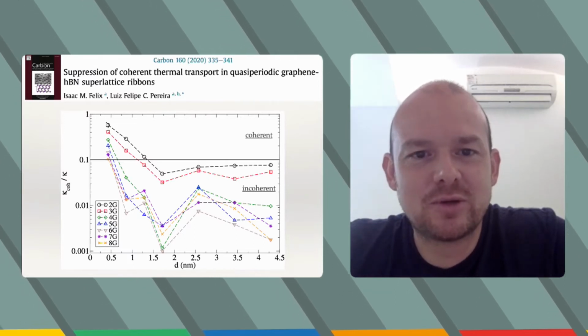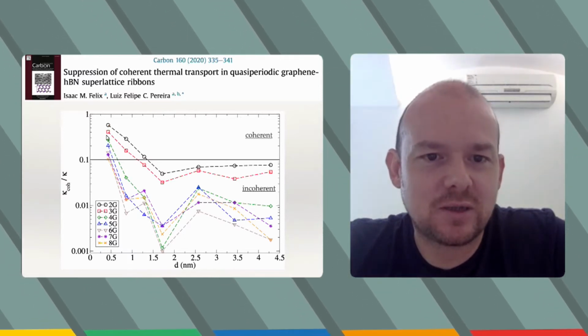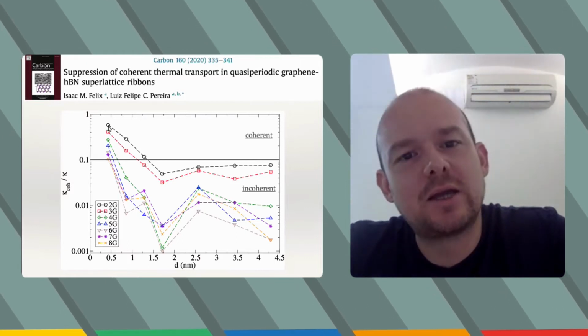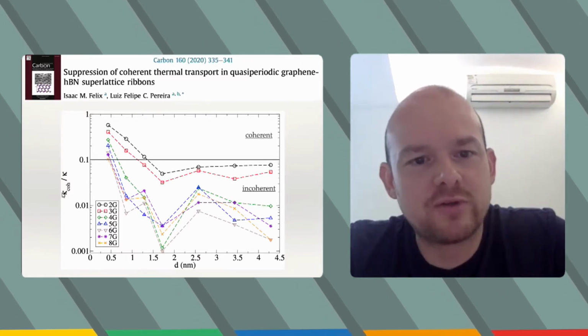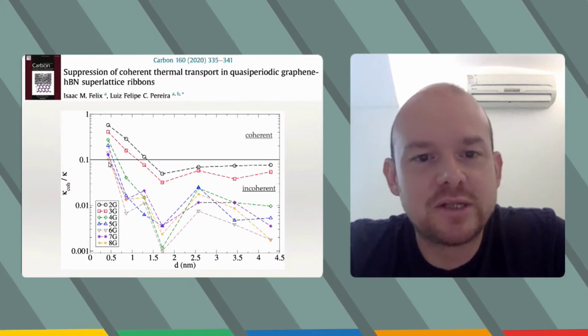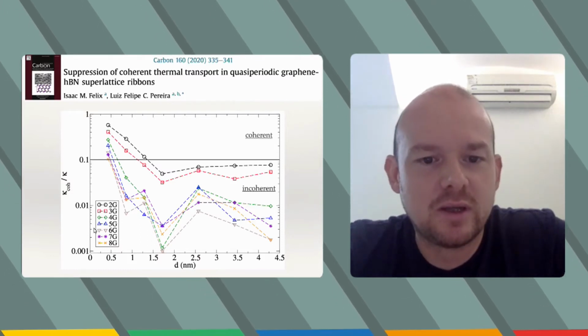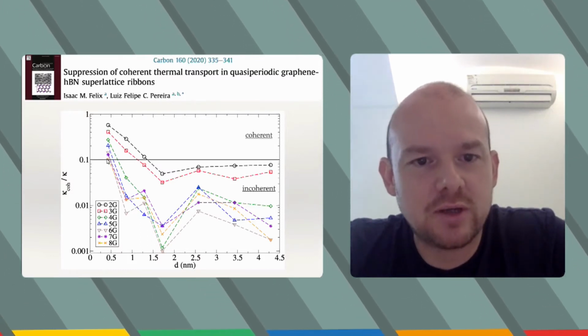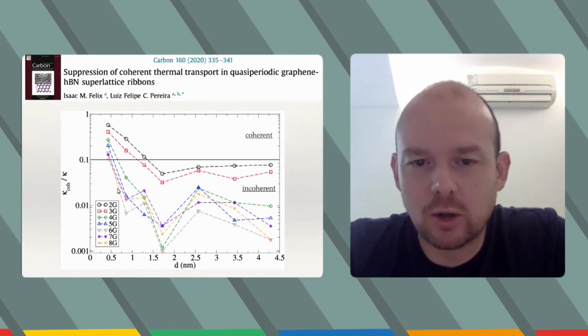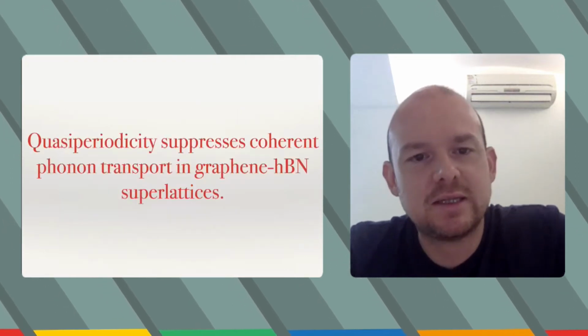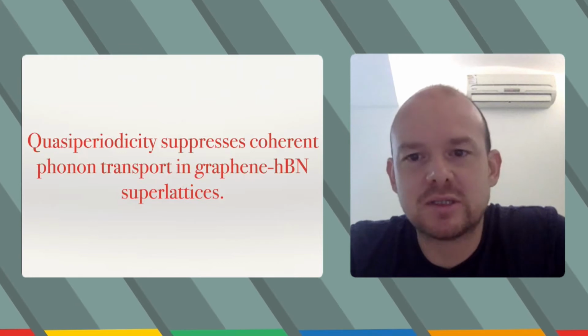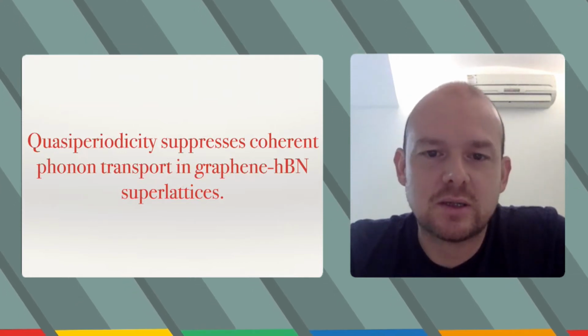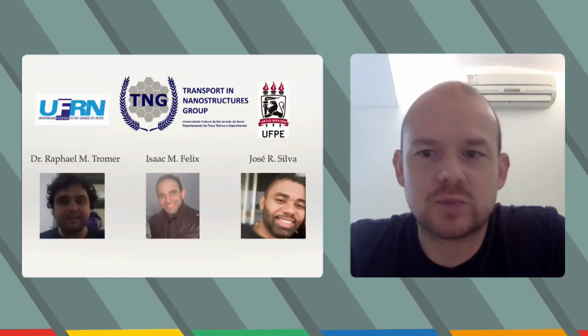As we increase the generation in this quasi-periodic sequence, the contribution of coherent phonons to the thermal conductivity decreases considerably. So even for the 8th generation here, the transport is always incoherent. So our conclusion is that the presence of a quasi-periodicity suppresses coherent phonon thermal transport.